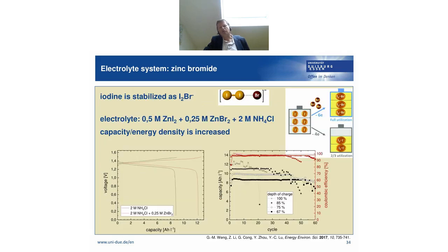It is interesting to note that in the triiodide ion, iodine, here in yellow you see the iodine molecule, is stabilized, and this really wastes one ion of iodide. So if we take, for example, zinc bromide, then iodine can be stabilized as I2Br minus. The molecule is here depicted in the middle. And like this, we can really unlock the full capacity, which is shown here qualitatively on the picture on the right top, when we can complex the ion with the bromine, then we can really oxidize and reduce all of the iodine.